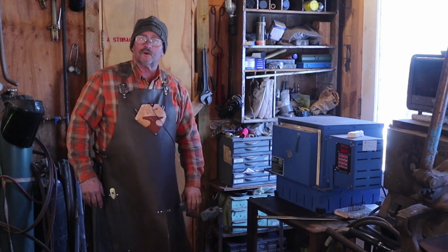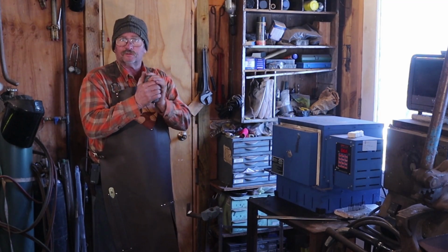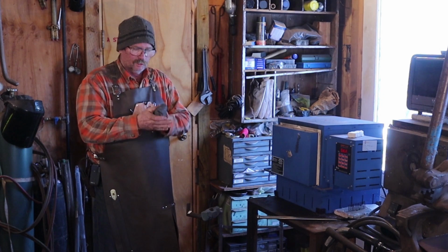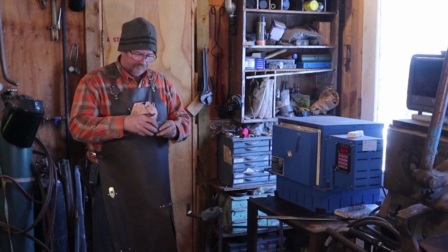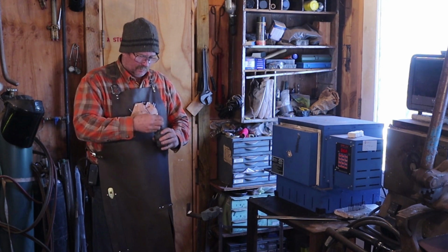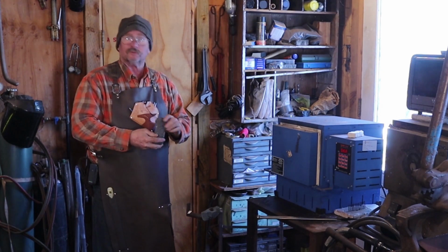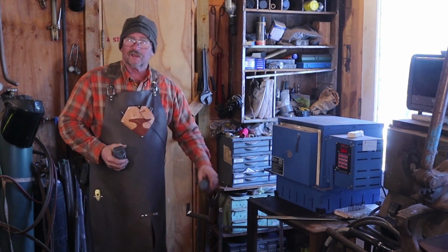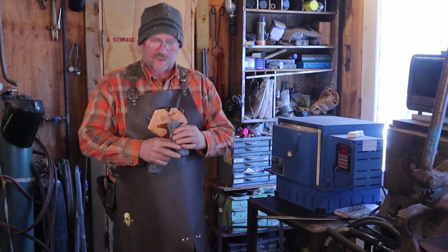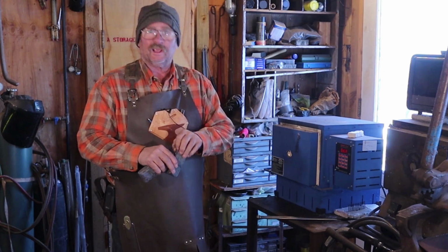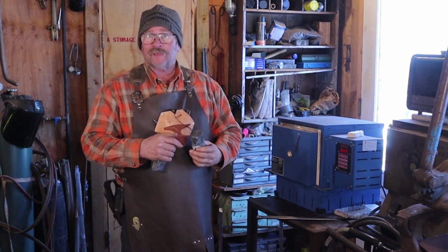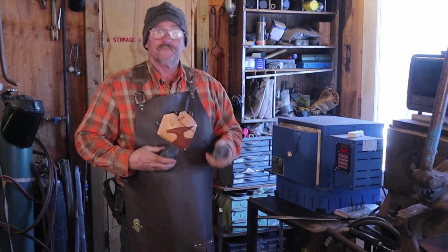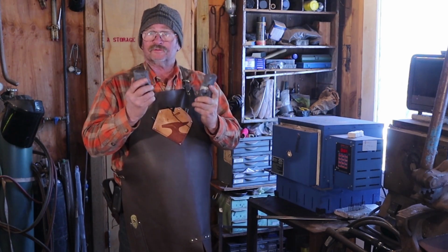Well, it's been a little over an hour, and these are still nice and cozy warm, but they're easy to pick up and hold. So they've cooled off very nicely. Now, a quick look at them. I don't see any cracks, which is what I always worry about right after hardening. Although air quench steels don't tend to crack as easily in the air quenching as do water or oil quench steels. So now the next thing to do is to temper these.